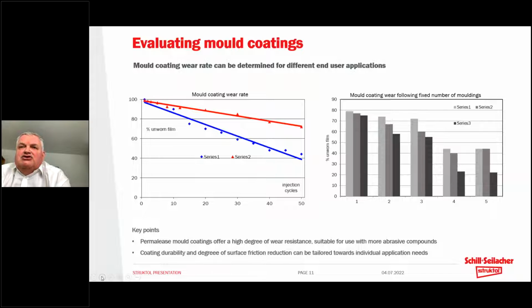So if we look on the right-hand side, the bar chart, 5 different compounds were evaluated, and the subsequent wear rate achieved for 3 different mold coatings. And you can see compound 1, not so much mold fouling, all coatings perform relatively well. We retain a high degree of film consistency, if you like, after a number of moldings. But contrasting that against compounds number 4 or 5, we can see under this example that mold release coating number 3, series 3, is definitely not very durable, perhaps providing a greater degree of slip, and is more or less completely removed after the fixed number of moldings. So depending on the type of compound that we want to inject, and whether we need to balance durability, the ability of the coating to last for a higher number of cycles, against the release effect, we can achieve different performance criteria depending on the coating technology that we choose. Next slide, please.